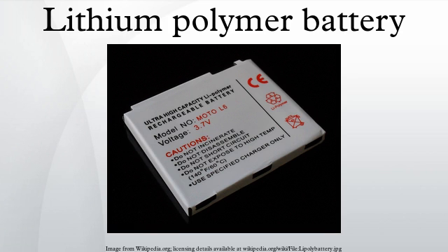LiPo cells are affected by the same problems as other lithium-ion cells. This means that overcharge, over-discharge, over-temperature, short circuit, crush, and nail penetration may all result in a catastrophic failure, including the pouch rupturing, the electrolyte leaking, and fire. All Li-ion cells expand at high levels of state of charge or overcharge due to slight vaporization of the electrolyte. This may result in delamination, and thus bad contact of the internal layers of the cell, which in turn brings diminished reliability and overall cycle life. This is very noticeable for LiPo, which can visibly inflate due to lack of a hard case to contain their expansion. Compared to cylindrical Li-ion cells, LiPo lack integrated safety devices such as a current interrupting device or a positive temperature coefficient material that is able to protect against an over-current or an over-temperature.